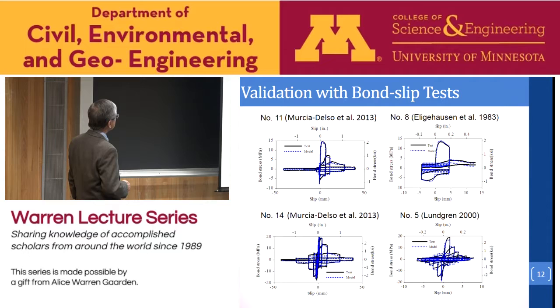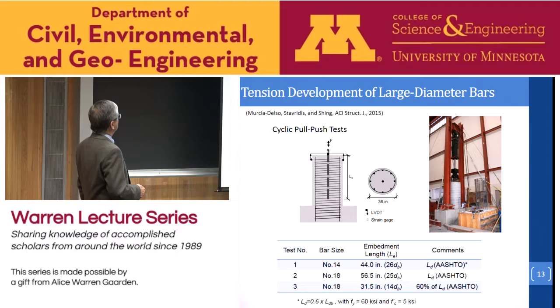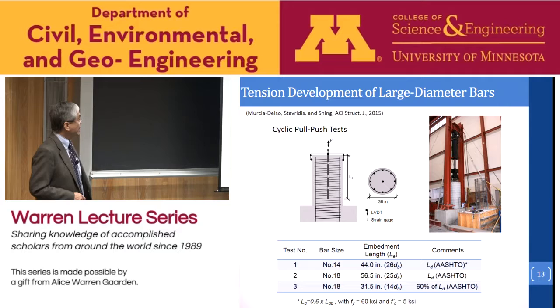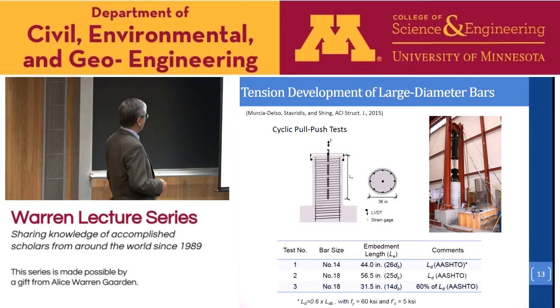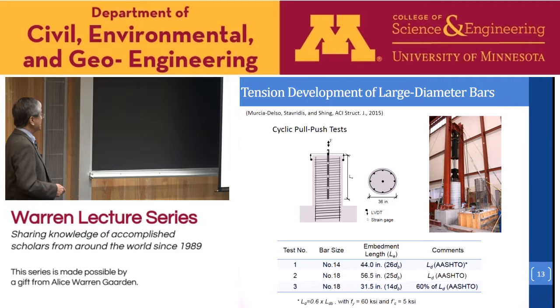Then the next test we did was on the development length test. So we have a long development length, okay, for the bars, embedment length. And we tested three specimens for number 14 and also for number 18 bars. They are very large. Now, essentially, we want to evaluate whether the provision provided by the AASHTO codes on the development length is appropriate. Okay, so the third test specimen, we reduce this development length to 60% of what is required in the AASHTO. And this is calculated based on the nominal strength of the bar, 60 KSI, and the actual strength of the concrete we are using.